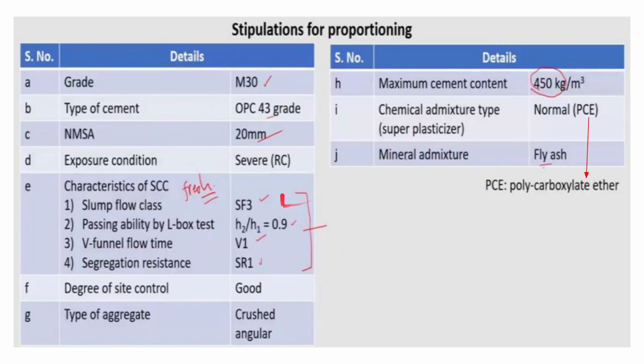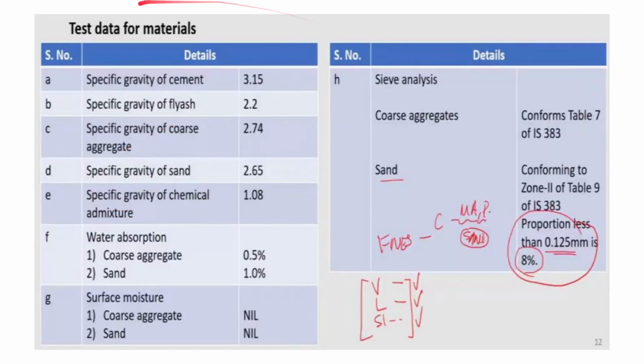So here are some of the stipulations, the values and requirements for design. The grade is M30, the type of cement is OPC 43, the nominal maximum size of aggregate is 20 mm, and the exposure condition is severe, reinforced concrete. These are the SCC flow characteristics: slump flow class SF3, passing ability 0.9, V funnel flow V1, segregation resistance SR1, degree of site control good, type of aggregate crushed angular, maximum cement content 450 kg per meter cube. The chemical admixture type is normal, polycarboxylate ether, and the mineral admixture used is fly ash. And these are some of the test data obtained for the material proportioning. These are almost along the standard values only.